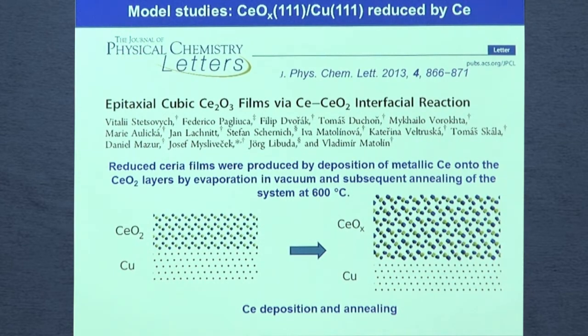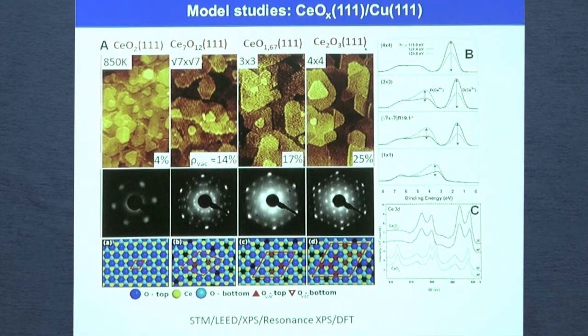Well, in the case of cerium oxide, we need to control two things: the stoichiometry and the morphology. Stoichiometry means to prepare ceria which is partially or fully reduced. For that, we proposed quite a new technique, the reduction of cerium oxide by cerium. Because cerium metal is very reactive, we first prepare a CeO2(111) buffer layer, and after that by depositing cerium, we are reducing the surface and increasing the concentration of Ce3+ states.